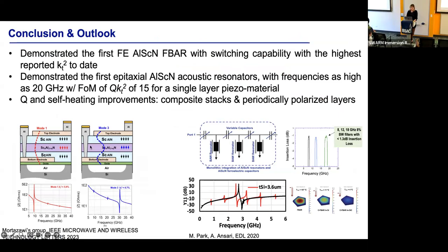Some of the solutions to improve the Q is adding multi-layer stacks where the polarization can be periodically switched. If you add up and down layers, with polarization up and polarization down layers, you can excite higher order modes without losing the coupling. This is one way that a lot of groups are looking at for scaling up the frequencies without losing the Q and the KT squared.